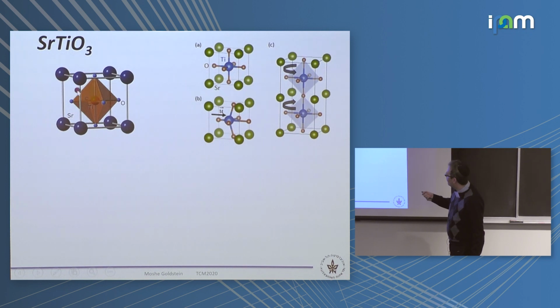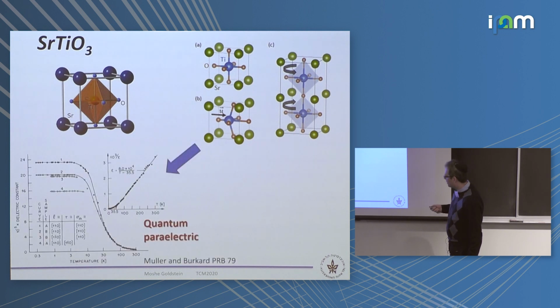And now, if we look at it, we can look at the phonons, or different ways that the lattice can be distorted. So one thing that could happen is that the titanium will shift, and because titanium is charged in this lattice, this is going to create an electric dipole moment. So this would make the material ferroelectric, and it turns out that this material is almost a ferroelectric. As you decrease the temperature, the dielectric constant rises to about something like 20,000, but it doesn't diverge, so it doesn't become ferroelectric, but it's a quantum paraelectric very close to some ferroelectric critical point, which you can reach by doping and other means.